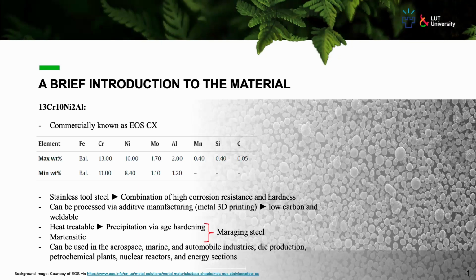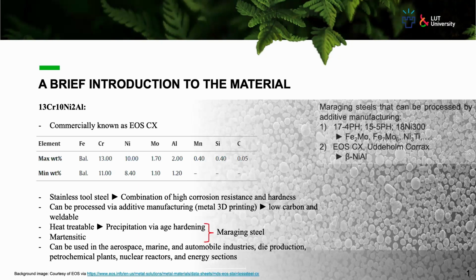However, the importance of this material and similar other powders is that they literally divide the precipitation hardening steels that can be processed by additive manufacturing into two different eras: before the emergence of these materials and after that. Before that, we had these classic 17-4 PH, 15-5 PH, or 18 nickel 300, which is commercially known as MS1, as the metal powders that are considered for 3D printing, and that can be used as tool steels.